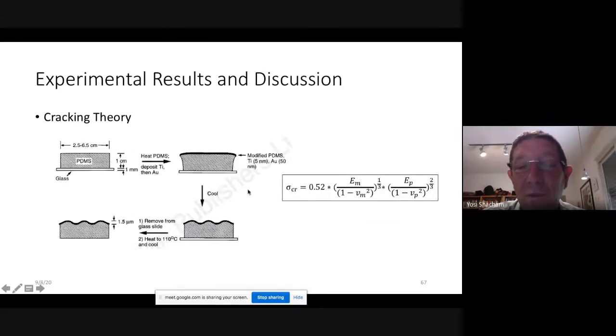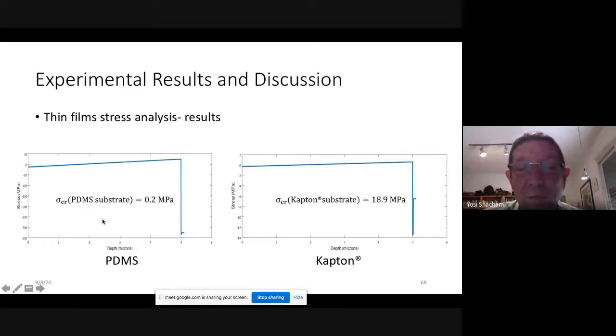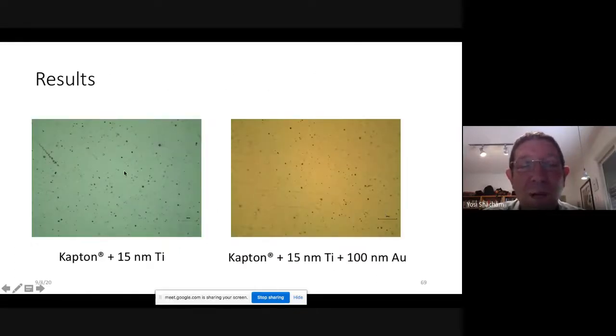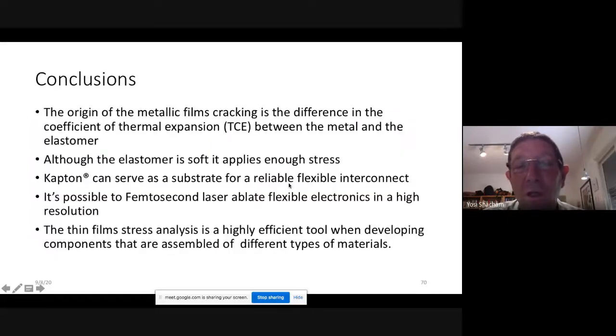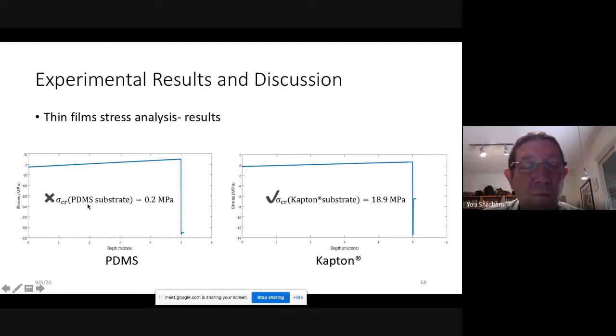stress dropped significantly. And just to give you the mechanism of cracking, if you have a PDMS, you put on top of it the metal, and when the device is cooling down, this is applying a force, and you have something called wrinkling. It's a non-linear phenomenon, and this is the critical stress for wrinkling. This is taken from a textbook, and these wrinkles break here on the bottom of the metal. And this is the critical stress: for PDMS it is 0.2, and for Kapton it is 18.9, which means, as we found out, that if we deposit it on Kapton, no cracks, nothing. Or alternatively, we change the composition of the PDMS to increase the Young's modulus of the PDMS and to reduce the coefficient of thermal expansion. And then we solve the problem.